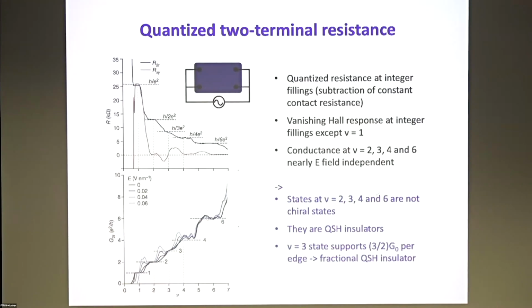So the 2, 3, 4, 6 states cannot be chiral states because of the vanishing Hall response. And with this geometry, the filling factor 3 state is very special because each edge contributes a 3/2 conductance quantum resistance. So it implies a fractionalization in this case.